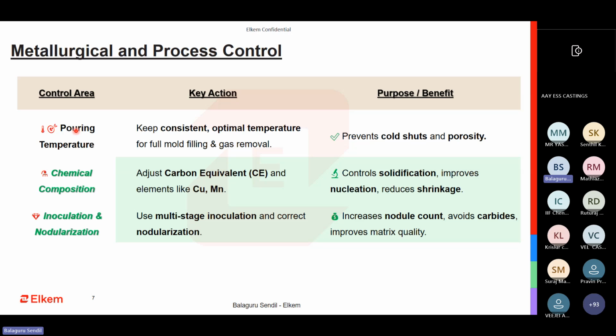If you are able to manage the graphite properly, because when graphite comes out, it gives heat, the natural shrinking of metal can be compensated. So it is very, very important that you are able to control when the carbon is coming out as graphite, at what stage. If you are able to do these things, then you can actually have very small risering designs in your castings. To do that, the most critical is our pouring temperature. It must be as low as possible.